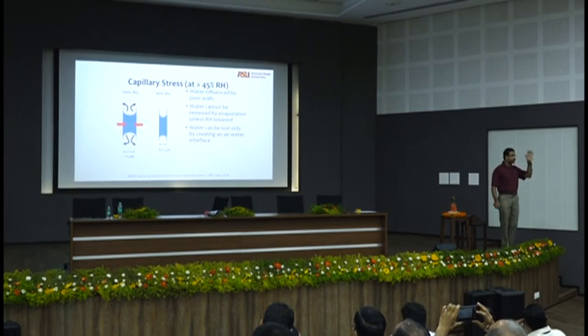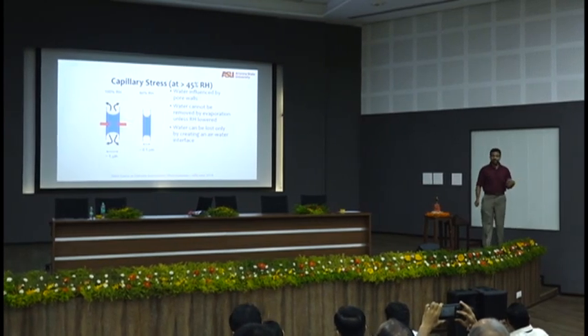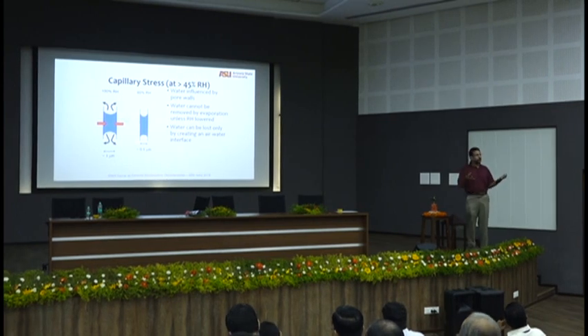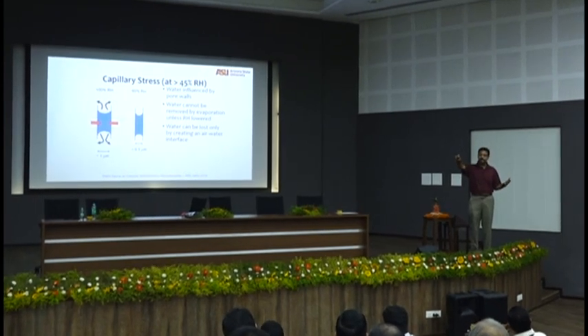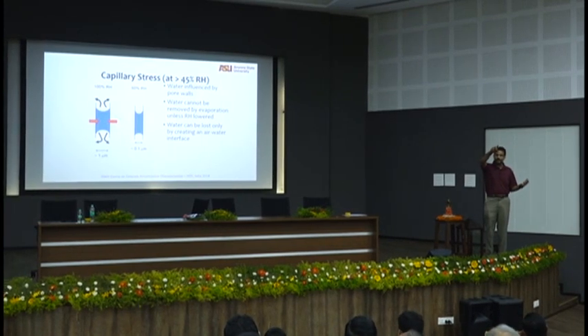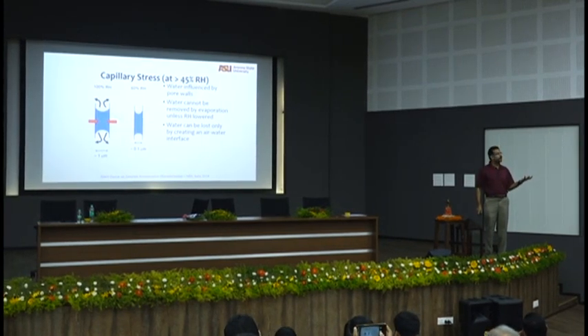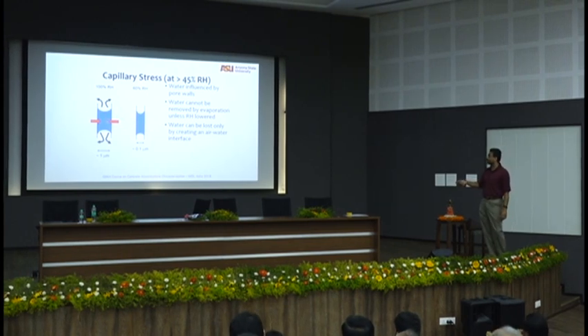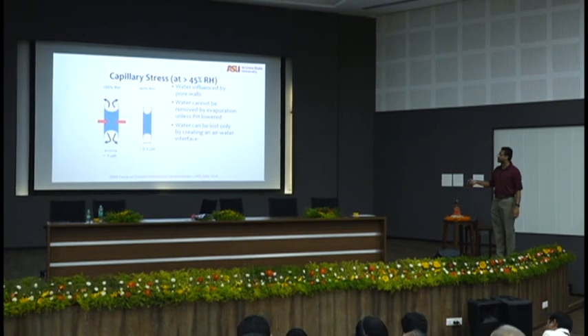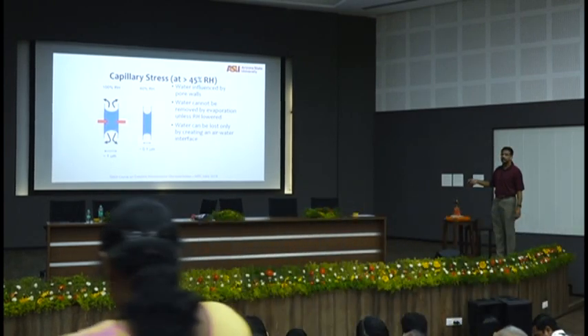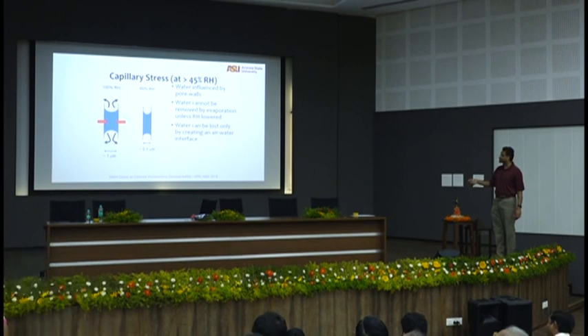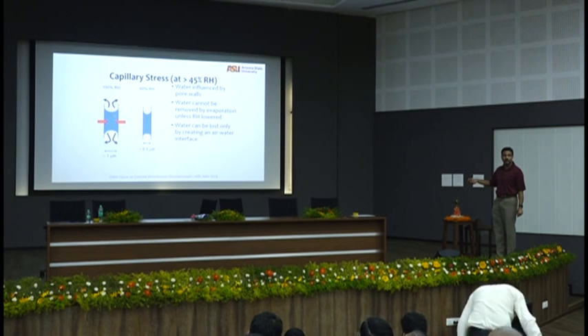Capillary stress mechanism happens only at a higher RH. Which means, remember, water from capillary pores will go away. Remember the stage 2 that ends at about 45% RH in that picture? Capillary water will go only until about 45% RH. So you really don't worry about anything else until then. Capillary stress. Water is influenced by pore walls. Very simple. You see this meniscus? When water goes away, the pore walls try to shrink. This is a larger pore, this is a smaller pore. Larger pore at 100% RH, this pore dries off. If the RH starts to go down, smaller and smaller pores dry off.